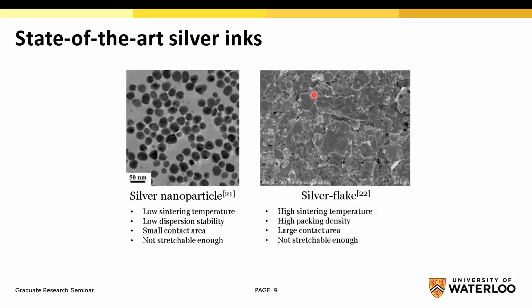State-of-the-art silver inks have either silver nanoparticles or silver flakes. Silver nanoparticles, as you can see, are circular particles on the nanometer scale, usually lower than 100 nanometers. Since they are really small, they have a really low sintering temperature because of their high surface energy. But also because of that high surface energy, they have really low dispersion stability, so you also need to use capping agents for them. And there is a small contact area. You can see that between each nanoparticle there is a very small contact area, known as dot-to-dot contact,